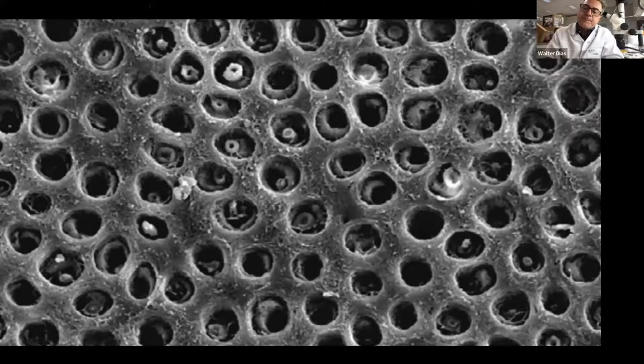What you see here is a case where you have much less intertubular dentin and also etched. That's why today we're really trying to avoid etching sound dentin, because when you etch the dentin like this, now you have to saturate all the surface area with the adhesive. You have to wait much more time. The drying time is much longer. And also you have less quality because you have less intertubular dentin, the dentin in between the tubules, which is where most of the adhesion comes from. So it's a lose-lose situation.